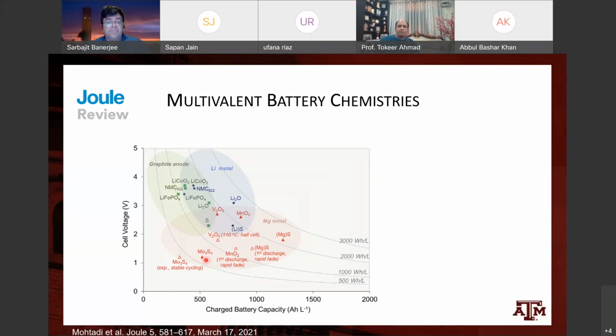Most of the magnesium cathodes, the one that is perhaps the most well developed, are these extremely good Chevrel phases, and you can get very good stable cycling from these Chevrel phases, Mo6S8. The challenge with this is that the voltage is very low, right? Only about 1 volt, but you can get thousands of cycles. There's a lot of interest in coming up with better cathode materials, and that's what I'm going to talk about. We've been working in this area on materials that are higher voltage and potentially higher capacity.